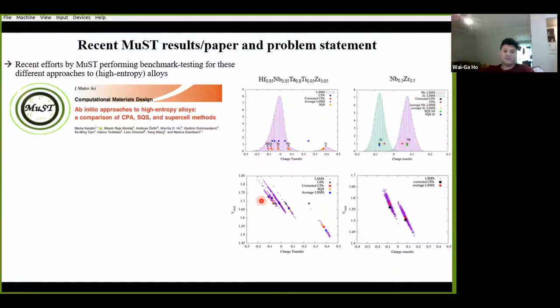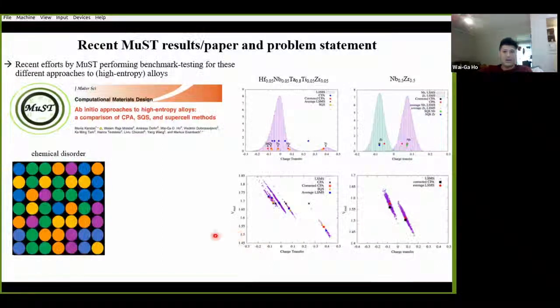But first, to generally understand what's going on here, let's take a step back and define a couple of things which are shown, like this Madelung potential, Vmad, on the y-axis down here. Well, this Madelung potential is just the local electrostatic potential for a given atom in this crystal, say the blue one over here. And this is just computed by summing over the Coulomb contributions coming from the remaining atoms throughout the rest of the crystal.